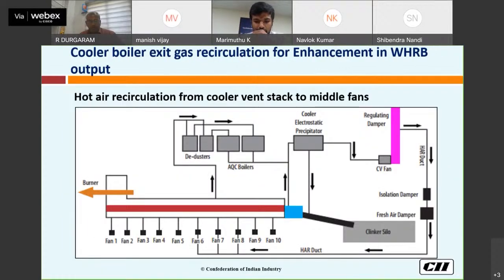This is the simplest diagram of the hot air recirculation arrangement, which is done at JK Lakshmi Cement. From the cooler vent stack, we have first a de-duster, and there is an AQC boiler. After that, we have an electrostatic precipitator. Whatever dust fines are collected in the ESP move to the clinker silo. Then the gas goes to the stack. From the stack, the gas, which might have a temperature of 100 degrees centigrade, is recirculated to the middle fans, fans 6, 7, 8, where the tapping for the AQC boiler is taken.